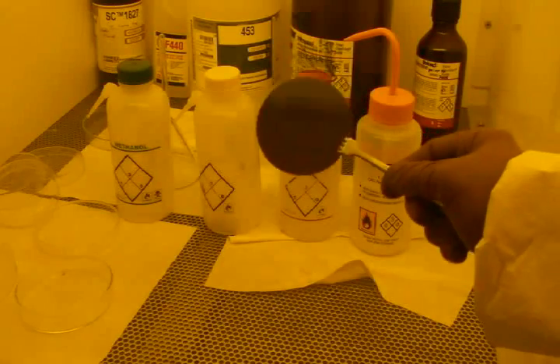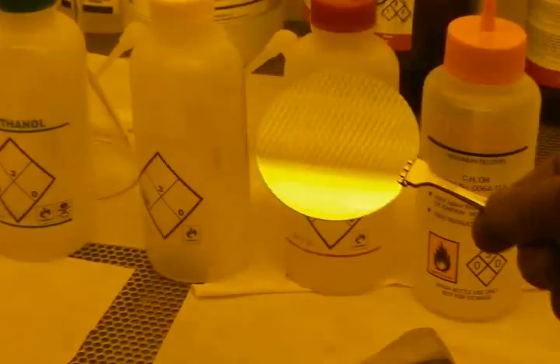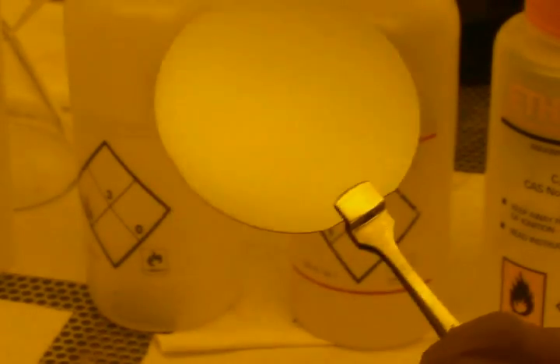A wafer is a thin slice of semiconductor material, such as silicon, used in the fabrication of integrated circuits and other micro devices. The wafer is usually cut from a larger crystal that has a definite orientation. The slice is then extensively polished to ensure its flatness and reproducibility in physical and chemical properties.